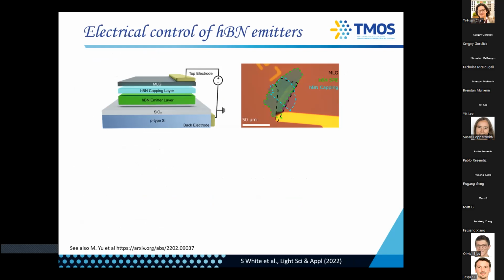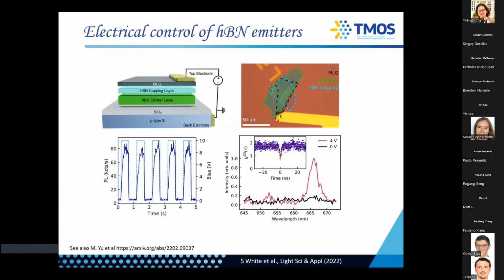Now here, the results were surprising. So when we applied voltage, we didn't see any stabilization. However, when we just scanned around on areas where we did not see any emission, when you suddenly turn on the voltage, you see an emission. Now, this is not electroluminescence, okay? The green laser is always on, but in addition, we also turn on the voltage. And you can see that the process is very reproducible. So the voltage is on, you have emission, voltage off, no emission, on, off, etc. And you can see an example here. So the black curve is a dark spot that has no photons. Once you apply voltage, you suddenly see an emission, and it's a single photon source.